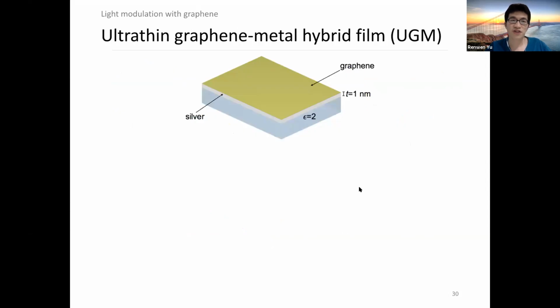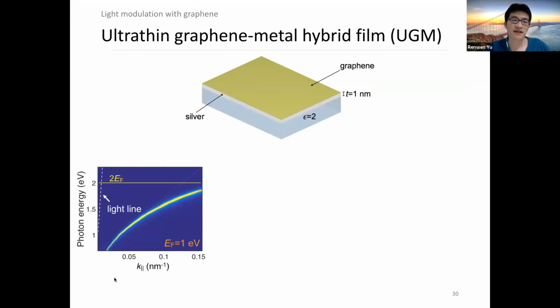So in order to achieve light modulation with graphene in combination with metallic structures in the visible frequency range, we came up with these hybrid structures, which are composed of graphene on top of an ultrathin layer of silver. When we calculate the plasmon dispersions of the hybrid modes supported by this hybrid structure, we can see that when graphene is highly doped, we can have very bright and sharp plasmonic resonances in a broad photon energy range.